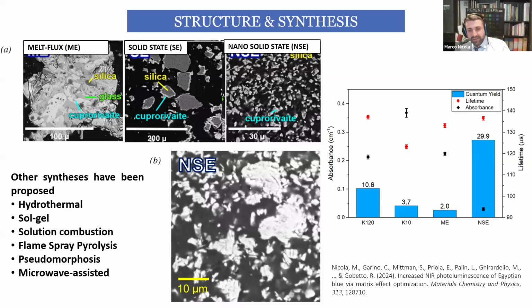This is one of the works, for instance, that we have made, making Egyptian blue that is three times more luminescent than commercial Egyptian blue, that is this one with K120 and K10, two commercial samples of Egyptian blue. The new synthesis made it possible to make Egyptian blue that is 3 times more luminescent, but we can arrive also to 5 times more luminescent, and we are improving and improving. Obviously, we can also try other kinds of synthesis, not based on solid state, but based on other philosophies. And in this American Ceramic Society, for sure you have a lot of ideas about those new paths that can give Egyptian blue with higher features. So this is an idea.